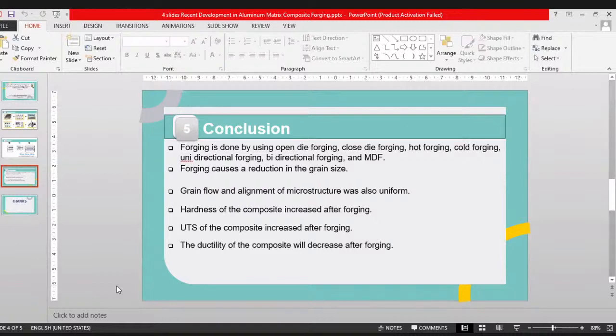Engineering strain before multi-directional forging was 20.1%, but after multi-directional forging, engineering strain was 15.2%. From this, we know that the ductility value is reduced.